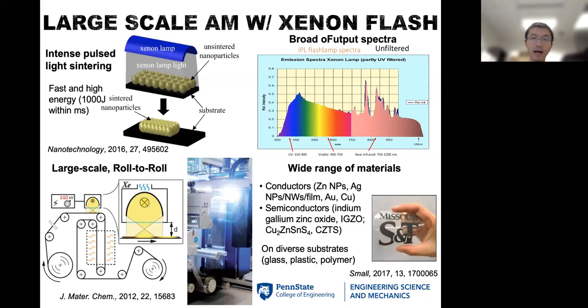So this is super nice. And initially we tried to use this one for the application of zinc nanoparticle because zinc is biodegradable. We want to sinter that into a conductive pathway, but we found out the challenge with that is zinc oxide on the outside surface will actually be detrimental because that material layer is not conductive. Sintering will be hindered and also the conductivity will be compromised.